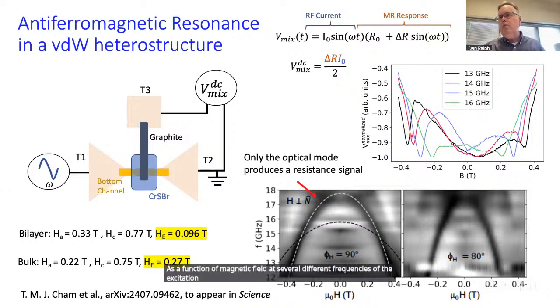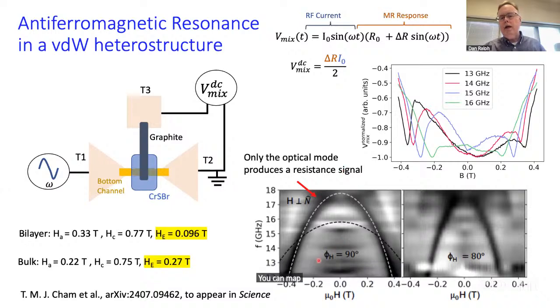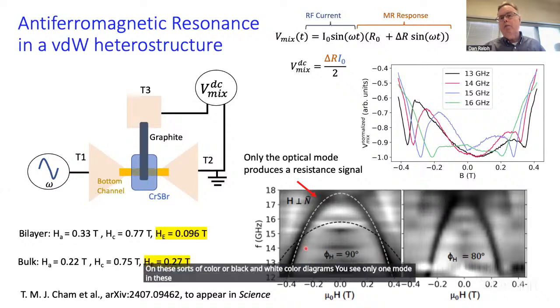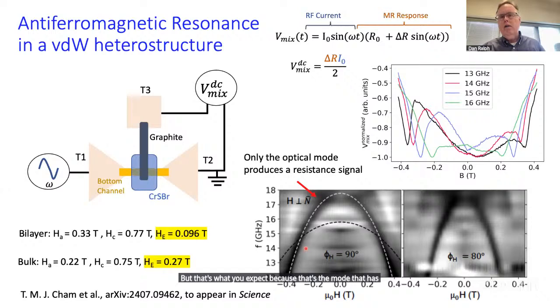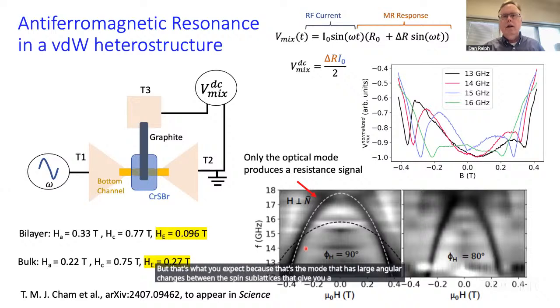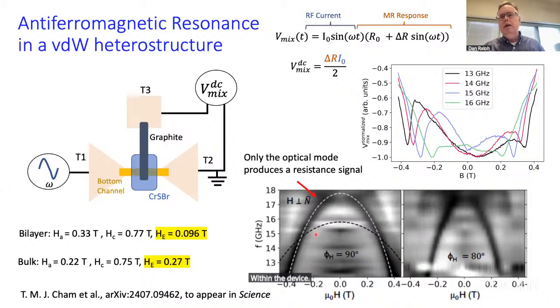You can see dips here at both positive and negative field that correspond to these resonances. You can map out what the resonance looks like as a function of frequency and magnetic field on these sorts of color or black and white diagrams. You see only one mode in these devices. You see the optical mode, but that's what you expect because that's the mode that has large angular changes between the spin sublattices that give you a change in resistance within the device. Within the device parameters we have, the acoustic mode would be along the dashed line here. We don't see anything.